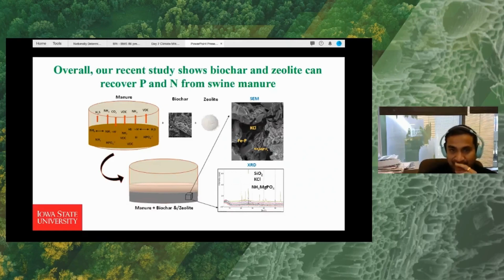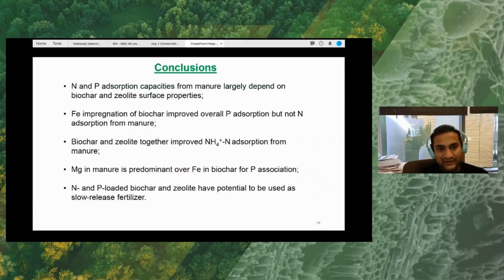So, overall conclusions. Nitrogen and phosphorus adsorption capacities from manure largely depend on the biochar and zeolite surface properties. Iron impregnation of biochar overall improved the phosphorus adsorption, but not nitrogen. For nitrogen adsorption, we need a combined system of biochar and zeolite. Manure magnesium is predominant over iron in biochar for the phosphorus association. And the nitrogen and phosphorus loaded biochar and zeolite can be used as a slow release fertilizer, providing nitrogen and phosphorus to the crop plants.